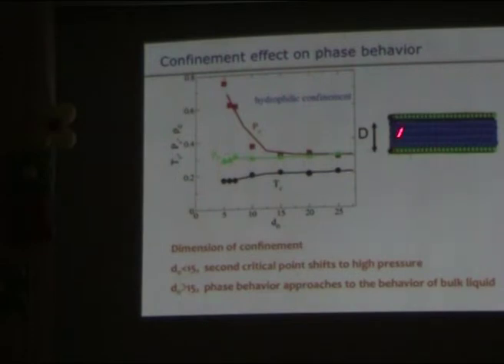As you separate these two plates further and further away, in the end the critical point should converge to the non-confined case. You can see that it's more or less around 15. This is the normalized parameter. So 15 is roughly about 7 to 8 layers of liquid in between. Okay, so lower than 15, the confined data cannot be overlaid on top of the bulk liquid data. But after that, it's more or less okay, at least in terms of this critical point, the critical pressure.